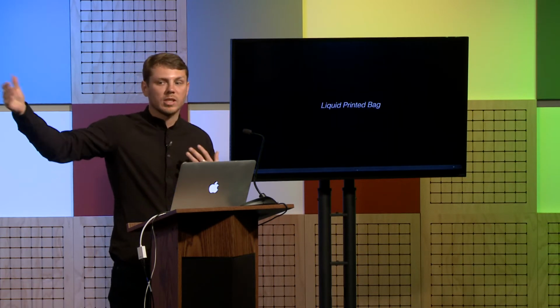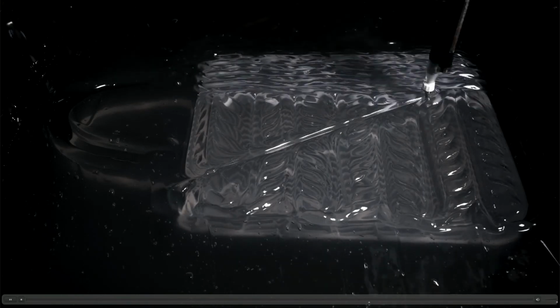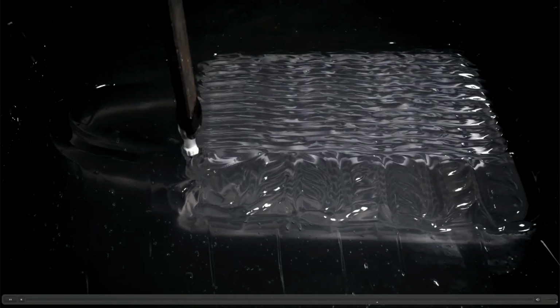So we can print small things like millimeter scale things. We printed a hammock, so a 10-foot long structure. You can print big things, small things. But maybe most interesting is the materials. So this is a beach bag that we printed for Design Miami, made out of silicone. So silicone is interesting because almost no other 3D printing process can print with silicone, but we can print with a wide range of materials, all industrially off-the-shelf materials. So no strange, our own complicated mix of materials.